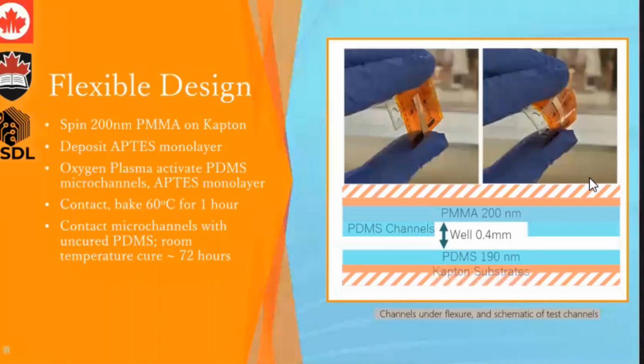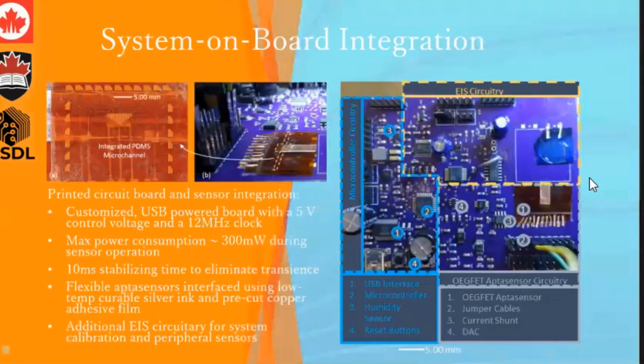The annealing steps, we have tried to keep close to room temperature. Like the PDMS curing is tediously long, but it doesn't require any temperature. And that's the APTES process for linking the microfluidic channel to the bottom surface. We still do a little bit of baking for the PMMA just to get the rigidity once the aptamer has been immobilized. But the aptamer limits the temperature exposure that we can do, which is why the readout part is where most of our current deliverables are focused on.